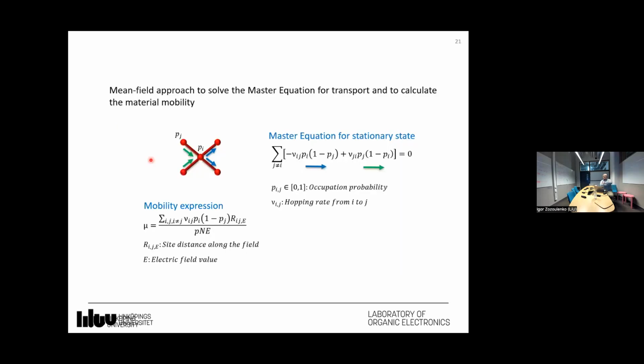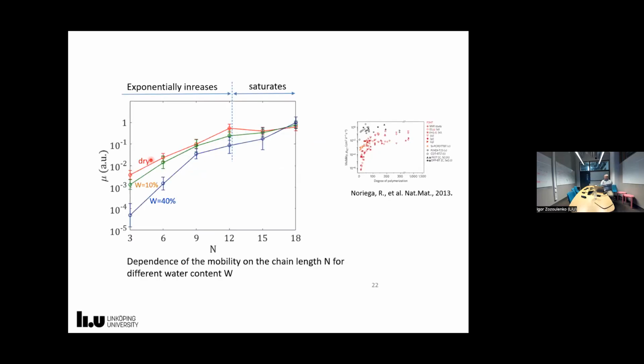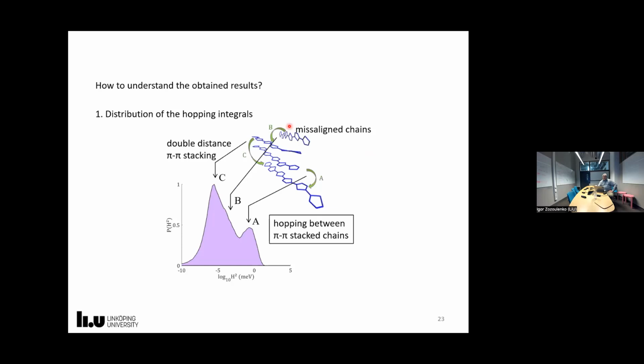And then we use the master equation to solve this system of transport units connected through these hopping integrals. And finally, these are our results. There are three curves corresponding to different water content, but let us just focus on the dry sample because we don't discuss water dependence. What we see is qualitative behavior very similar to what people see in experiment. Mobility for short chains is very low, and then it increases. And finally, when PEDOT chains become relatively long, it saturates. So we are happy that we reproduce the experiment.